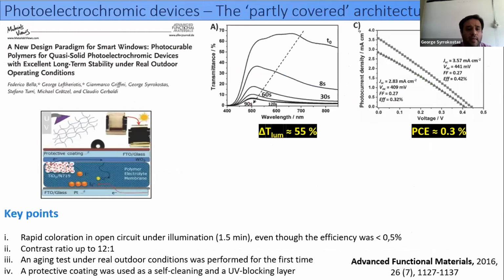Since then, we have examined a lot of parameters that can affect the performance of these devices. For example, the role of the electrolyte, its composition or its state. In this publication, we used a polymer electrolyte membrane, and we achieved an optical modulation around 50% and a photoconversion efficiency of 0.3%. More importantly, the coloration time was now less than 2 minutes, and that shows that the diffusion of lithium ions inside the polymer electrolyte is very efficient, and the faster coloration time is also due to the improved value of the photoconversion efficiency.